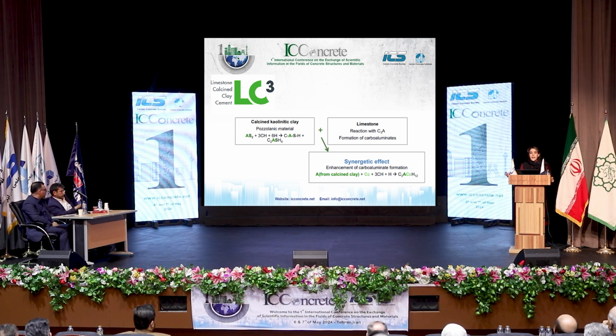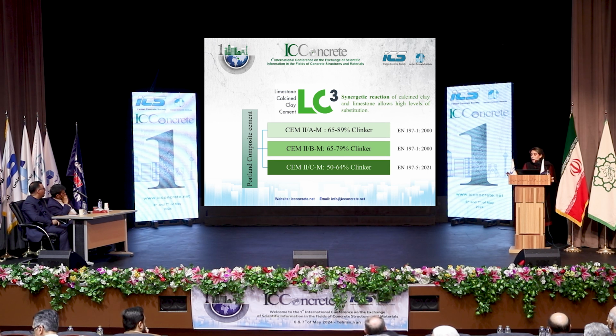In the LC3 system, three different reactions happen. First, the normal pozzolanic reaction of calcined clay with calcium hydroxide. The second reaction is between limestone, the calcium carbonate phase, and C3A. Another reaction is the synergic effect between the aluminate phase of the calcined clay and calcium carbonate, which results in the precipitation of carboaluminate phases, monocarboaluminate and hemicarboaluminate. This synergic reaction allows a high level of substitution in the LC3 system.